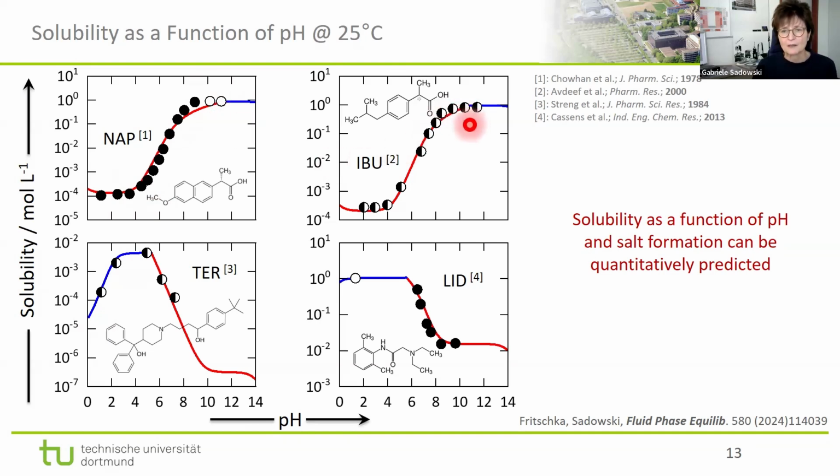And we also predicted the transition between the non-charged solid and the salt for the experiments where we don't have the experimental proof, but we are sure that this makes quite a lot of sense. So that means our message is, if you have a molecule that is able to dissociate, attract, or release protons, and the solubility is the one in water, always also consider investigating what the solid form is, and then, of course, use the solubility of that particular solid.